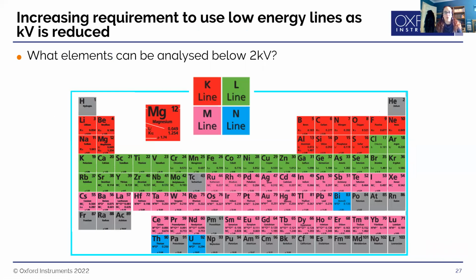Now, when you're looking at X-ray lines, you need to activate the X-ray line, and you can only activate an X-ray line if you're slightly more than 2 times its energy in the main beam electrons. So if your X-ray line is 1 kV, you need at least 2 kV, preferably 2.5 kV in your main beam in order to activate it and get the maximum emission from that particular X-ray line.